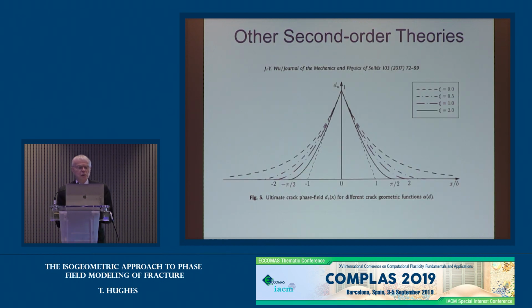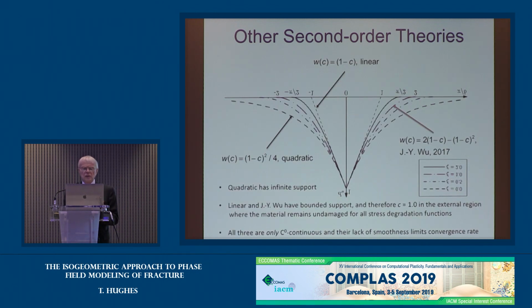These were compared by J.Y. Wu in an article 2 years ago. He did this and showed this graphically in terms of the damage parameter, which is, again, 1 minus the phase field. So I'll just flip it so that we can compare it with what we've seen before. And you can see here's the quadratic with its infinite support. Here's the linear, which has finite support, and that's why you're elastic outside of that support. And this is a linear combination of the two that J.Y. Wu proposed, and it also has finite support. Now, the finite support is an attribute here, and you can get elastic behavior for different stress degradation functions, but it still has the problem of the lack of regularity at the crack tip, and this limits convergence rate and accuracy. So from a numerical analysis standpoint, this is an issue.